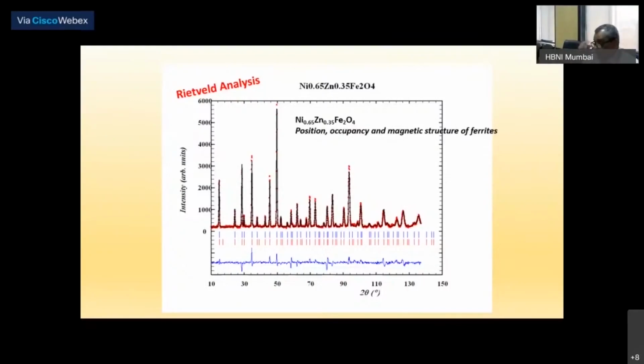Often we don't do a direct Fourier inversion of this data. You can see this data is plotted as intensity versus Q. Direct Fourier inversion will give me model independent data, but usually that doesn't happen because for that I need to have intensity over the entire Q range. That doesn't happen. So what one does, there are various programs available, but the best primary technique is that